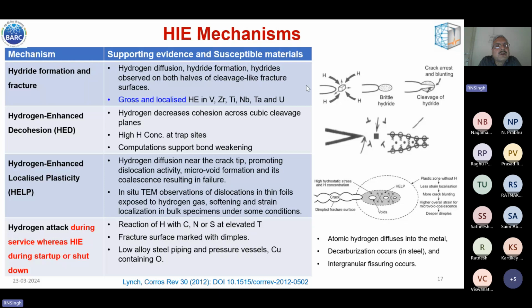Here you are talking about hydrogen enhanced local plasticity, no? Yes. Here I think we are talking about inside the grain only. What happens is that dislocation and hydrogen are interacting, and because of the presence of hydrogen near the dislocation, especially edge dislocation, they are able to glide very easily. So local plastic deformation takes place.